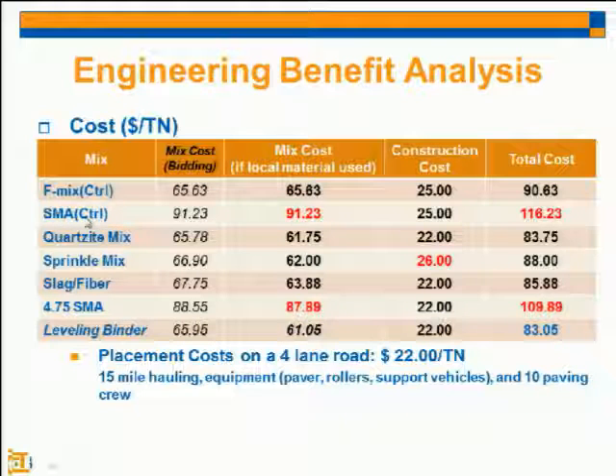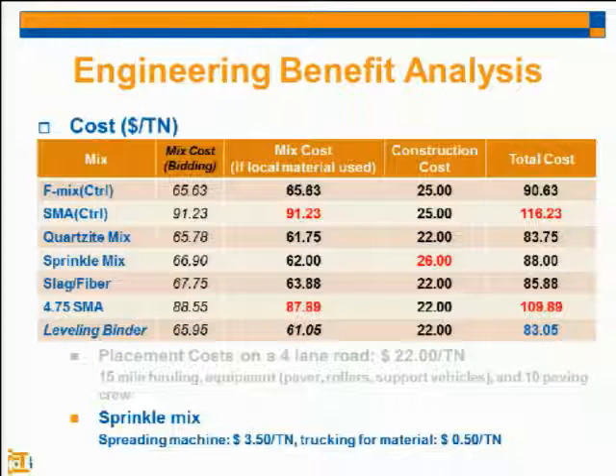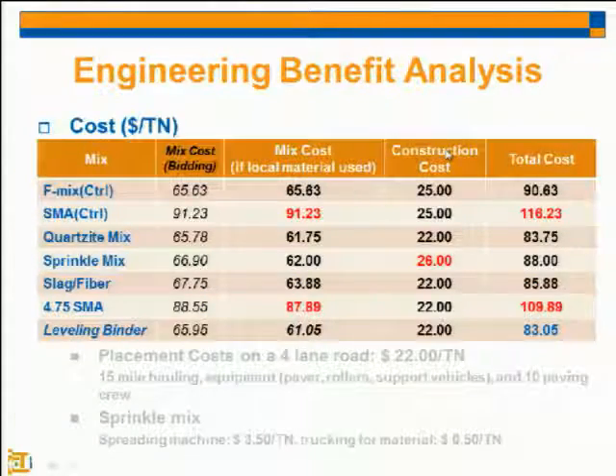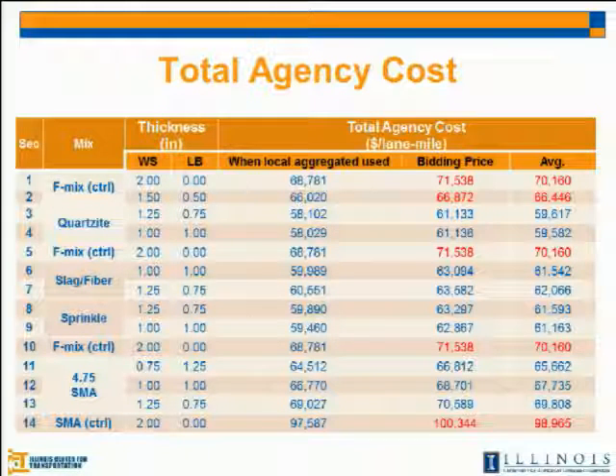You can see the control SMA provides the highest mix cost because it used the PG76-22 highly modified binder. And also the 4.75 SMA mixture. To have the small aggregate size, we screen the aggregate from the stockpile to get the 4.75 SMA. This additional process costs a lot, so that's why we have the very high mix cost here. Also, the 4.75 SMA contains 7.3% asphalt binder. And for the sprinkle mix, we need a spreader, so it increased the construction cost too.